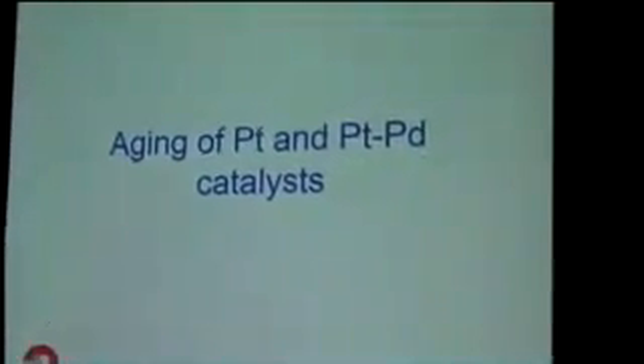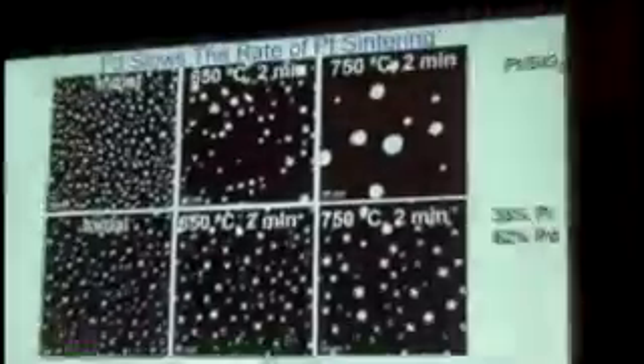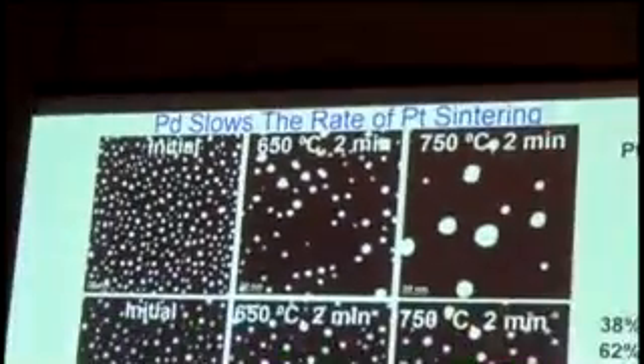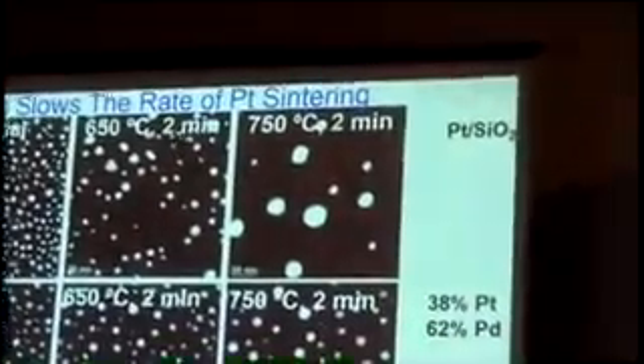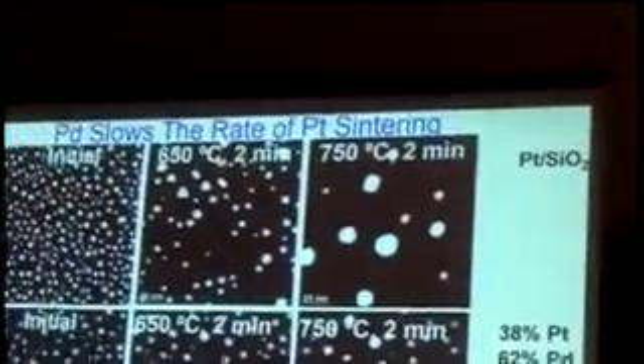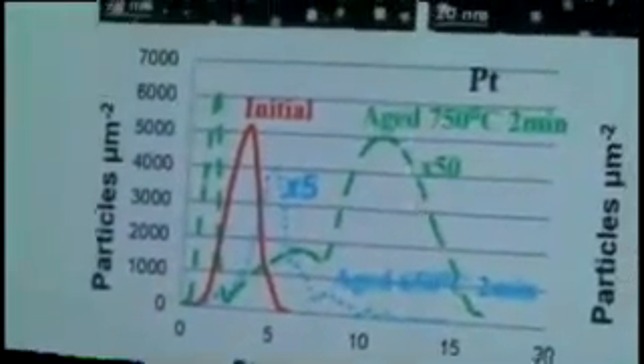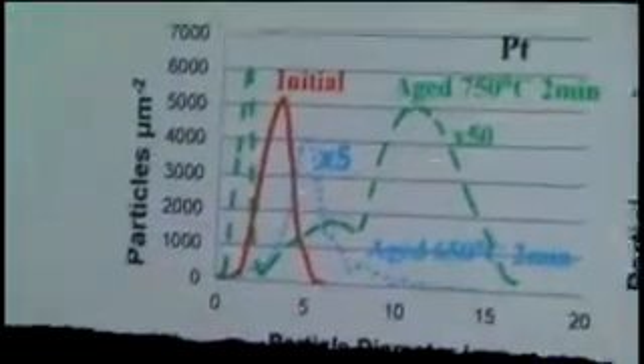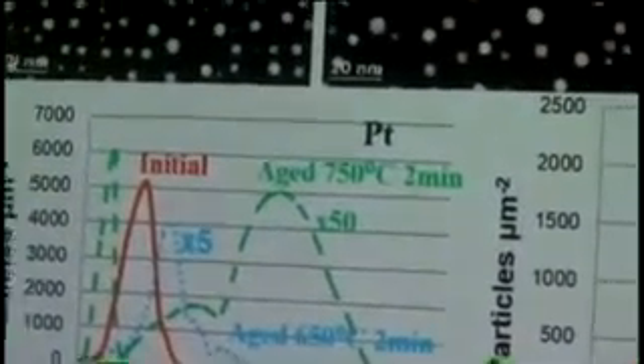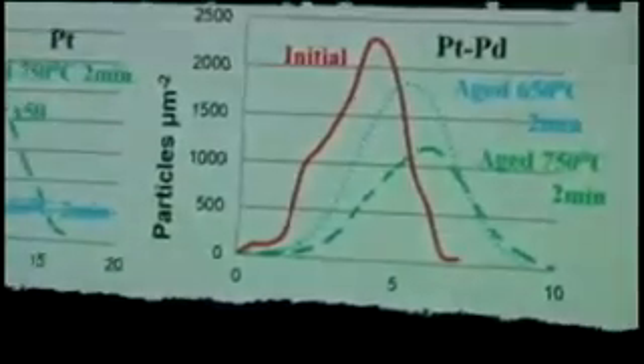Now what happens with platinum and palladium? So if you do platinum, you see aging, very rapid. At 650 C, 2 minutes already, a big change in the particle size distribution. And by 750 C, you start to see a little bit of bimodal distribution, some small particles and some large particles. That will happen with platinum alone. So platinum palladium, very well behaved, regular, uniform size distributions. So palladium does go to the platinum center. How does it do it?